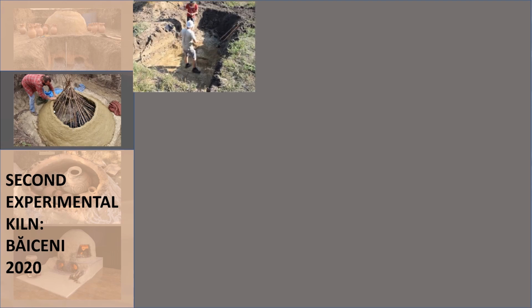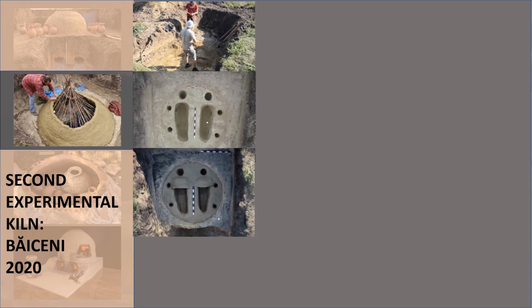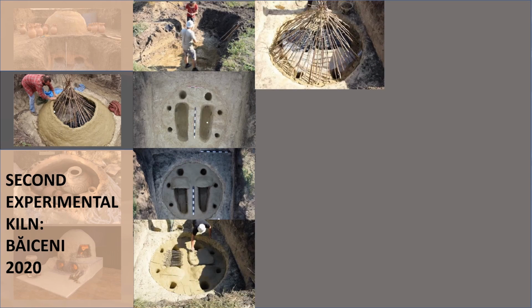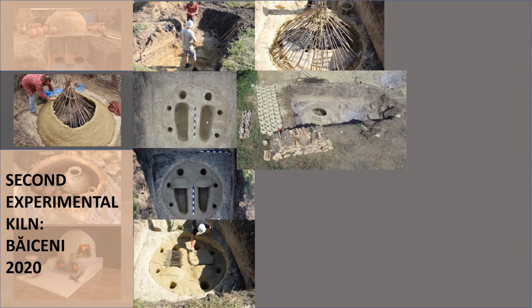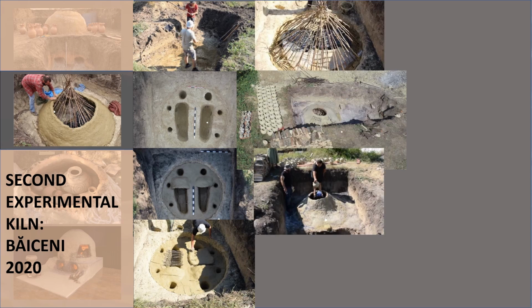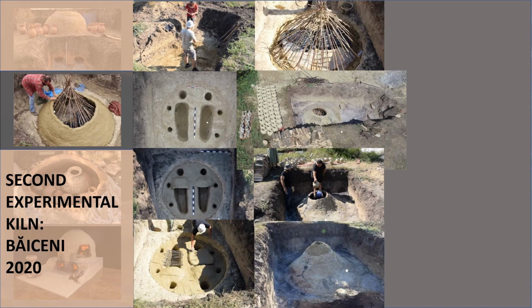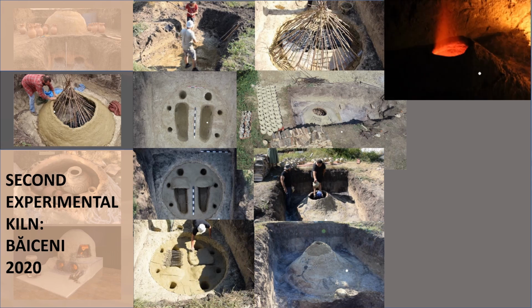The kiln structure was similar to the first, but with a crucial adjustment. A wooden frame was used to support the dome, which was then covered in layers of clay. Additionally, the kiln was filled to full capacity with ceramic vessels, ensuring optimal heat absorption. This firing produced significantly better results, reaching temperatures of 850 to 900 degrees Celsius across most of the chamber. The modified airflow system created a more efficient combustion process and allowed for higher and more consistent temperatures.